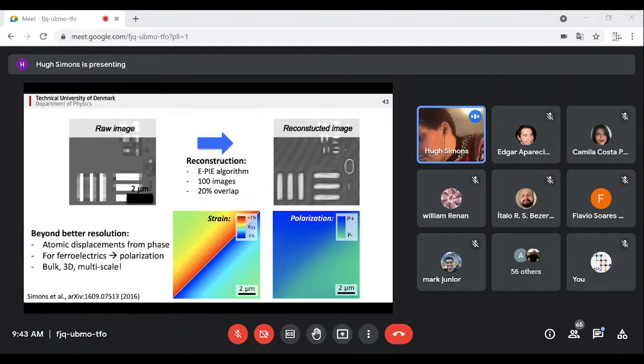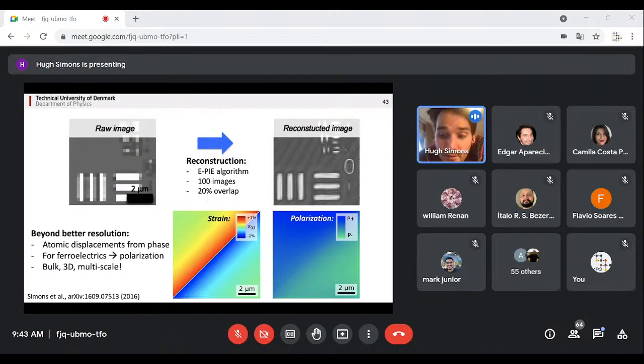And this is particularly interesting in our view for ferroelectric materials, because if you have sensitivity to how the phase of the X-rays is changing, you also have some sensitivity to the atomic displacements. And in a ferroelectric, or in fact any insulating material, the atomic displacements are related to the polarization of the material. So what we're really hoping down the track, and this is something we're really close to finalizing, although I think I've been saying really close for the last few years, but now I feel we're really, really close to being able to extract the polarization inside materials in 3D.